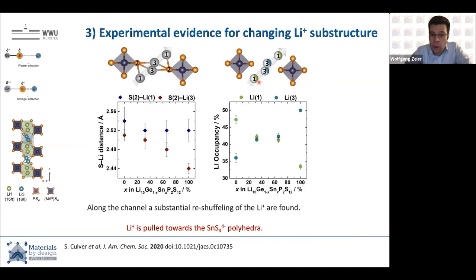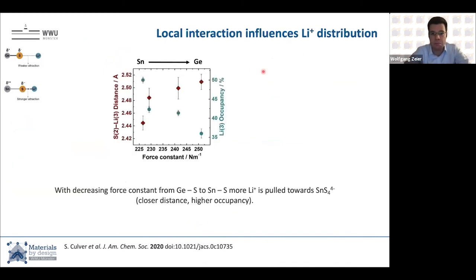What we see if we go from germanium to tin, the lithium 1 occupancy decreases and the lithium 3 occupancy increases. So it's not just the distance that changes, but the more charge density there is here, lithium gets pulled from lithium 1 to the closer distance lithium 3, and then the bond distance also changes, so it becomes just closer in bonding. So it seems that these subtle electronic changes reshuffle the lithium in this diffusion pathway. And lithium seems to be really pulled towards the tin S4 polyhedra.